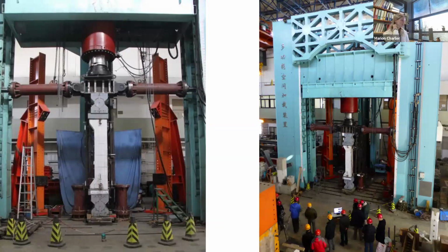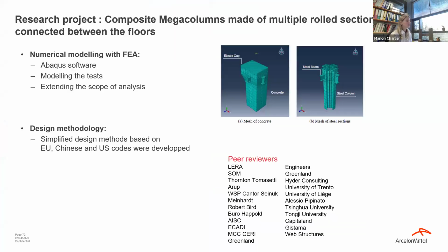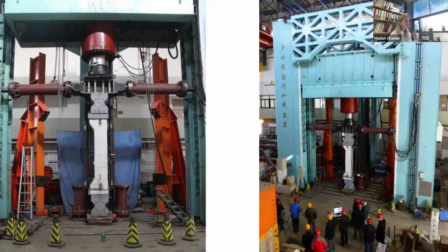Here you can see some pictures from the testing facility. So here are some pictures from the static tests. The actual capacity of that testing facility is 20,000 kilonewtons, so that's pretty huge. And with the picture on the right side, you can also have this idea of the magnitude of the testing facility. And the tests could demonstrate a good load-bearing capacity, good ductility, stiffness, but something also really important to assess was the good interaction between the steel and concrete. So the fact that we could achieve the composite behavior.